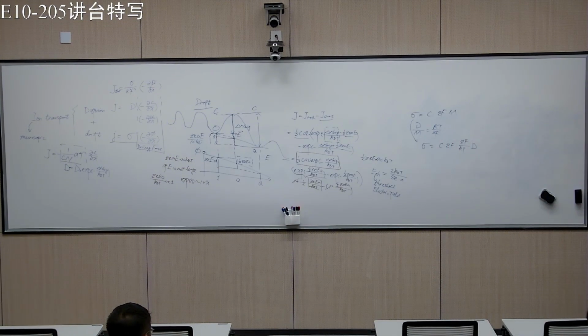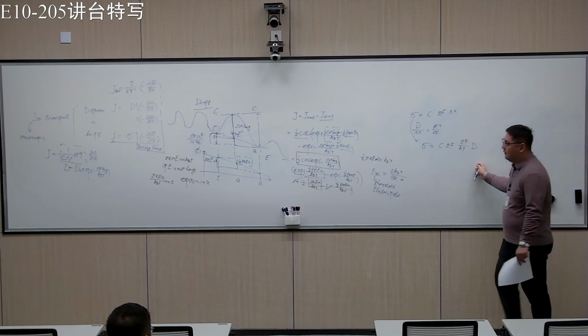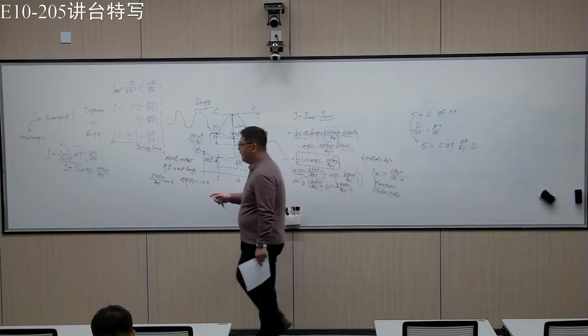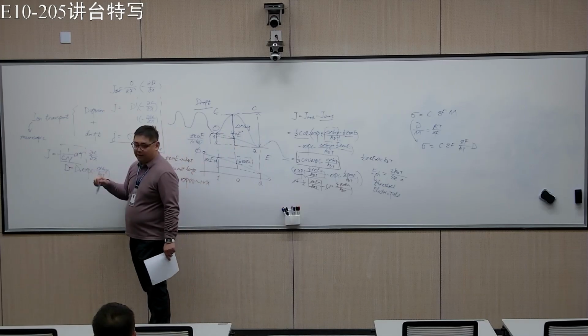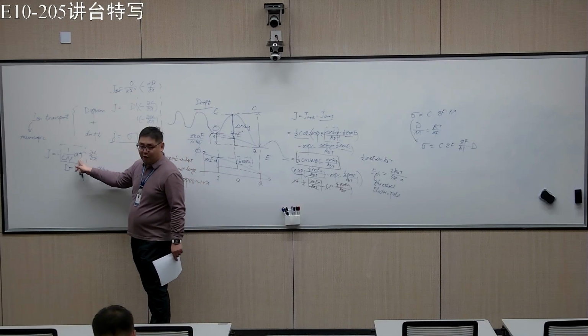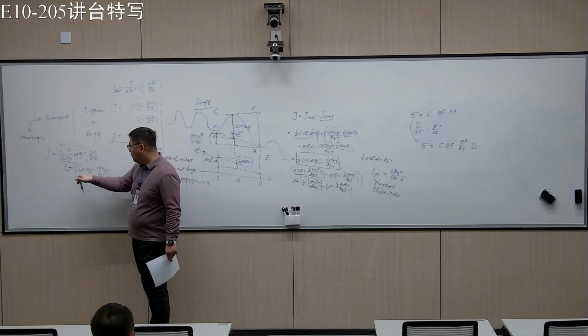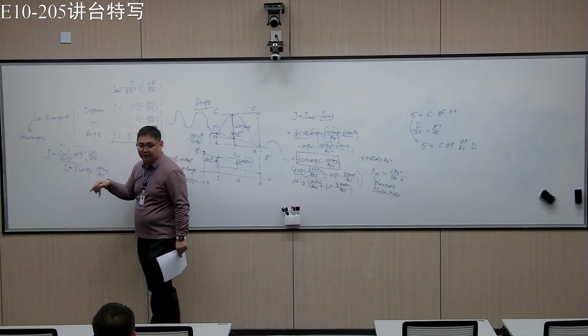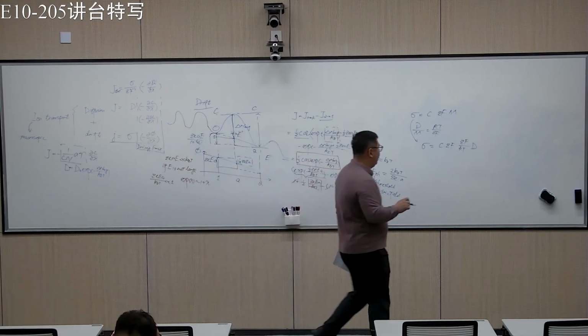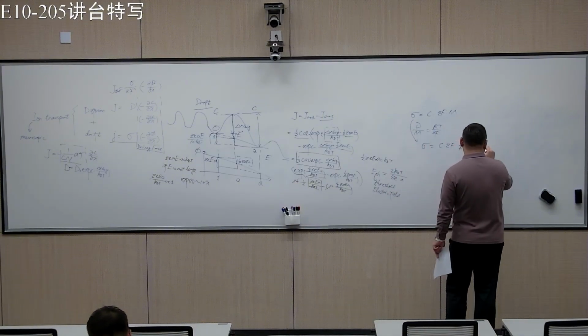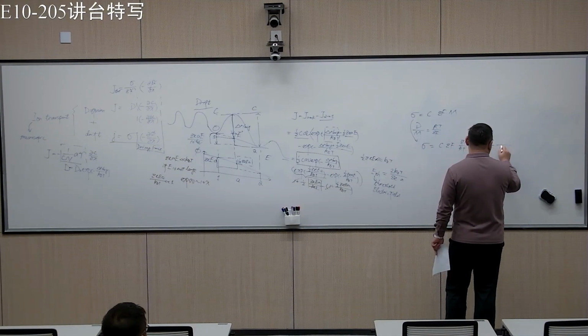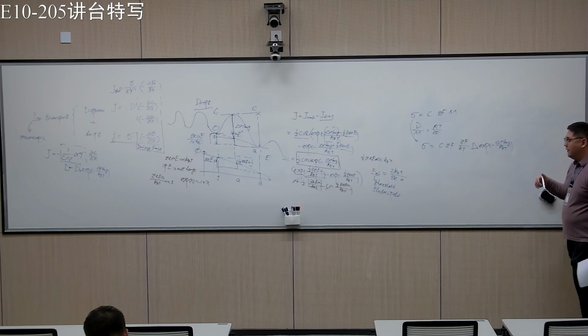All right. We know that D in this case is this part. Okay, so it has something to do with the hopping frequency. And then the hopping frequency is thermally activated. Okay, so then D is D0 times exponential of minus delta H migration over KBT. Okay, so this is for ions.